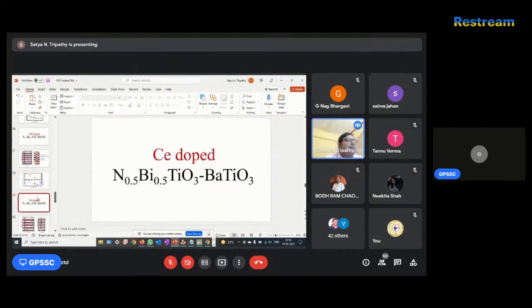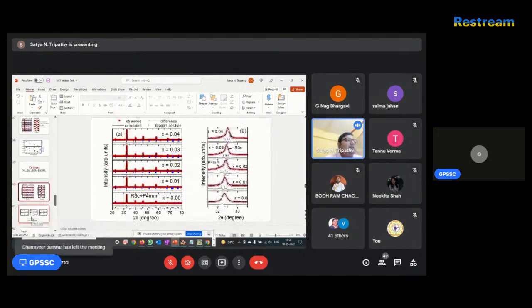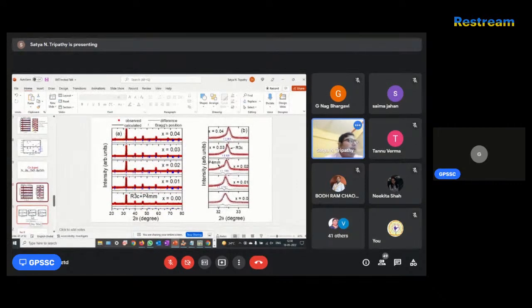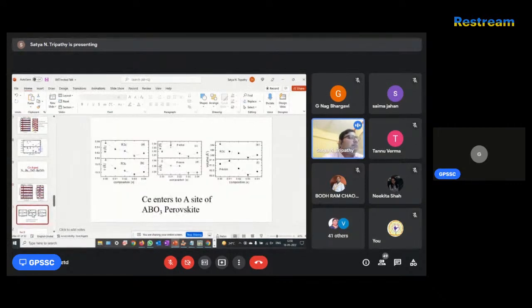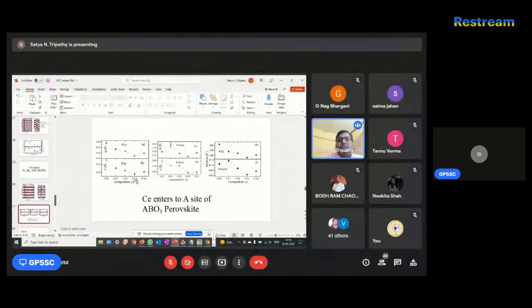So another system we also have is cerium doped sodium bismuth barium titanate. Okay, here cerium can go to the sodium, bismuth, or barium site, and I will show you what results were obtained. So this is basically your XRD pattern. These are the fittings we observed, and now I am going to show you the lattice parameters. So you see a and c in the R3C phase, a and c in P4MM, and volume. So here also we see that the cerium basically goes to, meaning a minimum is observed up to 0.03, and that is the critical condition. We saw maximum changes in the dielectric property. We obtain maximum strain there.